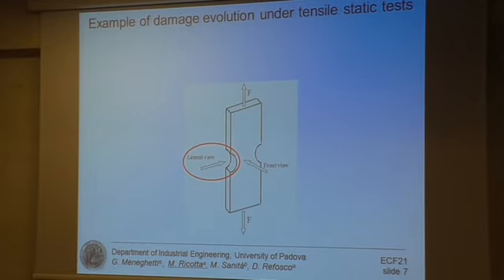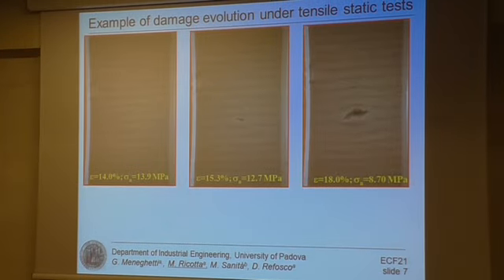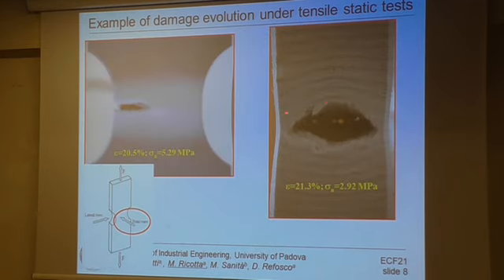Just an example here of damage evolution. We monitored the damage evolution from two different positions: a lateral view, in order to see what happens inside the notch, and a front view, in order to see what happens in the net section. Here we can see an example obtained in the case of totally recycled polypropylene and notch root radius equal to 10 millimeters. Here we are seeing the specimen from lateral view, therefore here we are inside the notch. We can see that damage evolution starts with several voids that grow, and some of them coalesce to form a single void that becomes very large at the end of the static test. And here we can see that the light is coming from the opposite side because the void is completely developed in the width of the specimen.